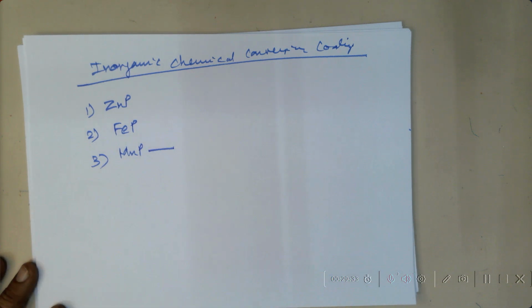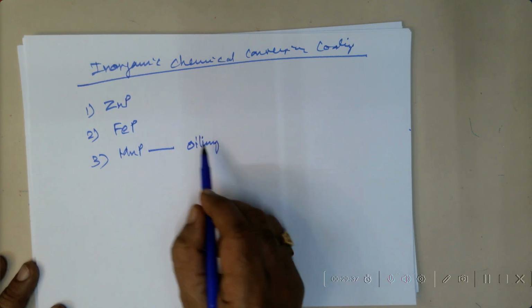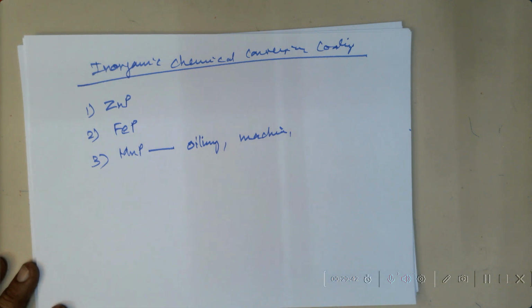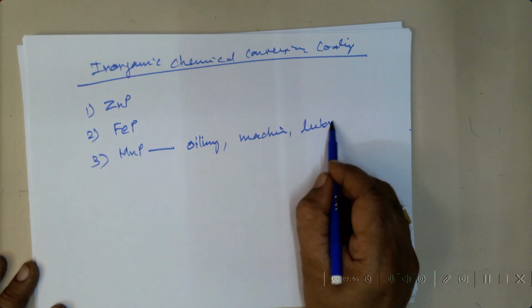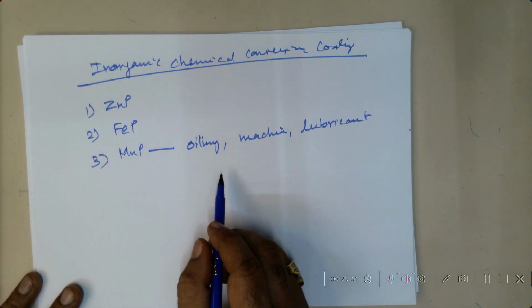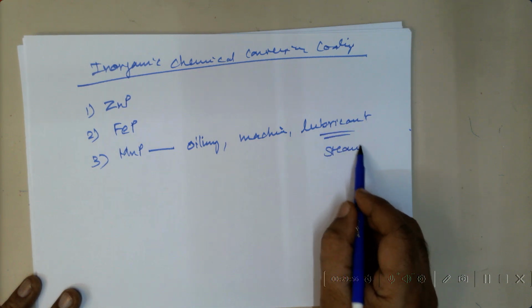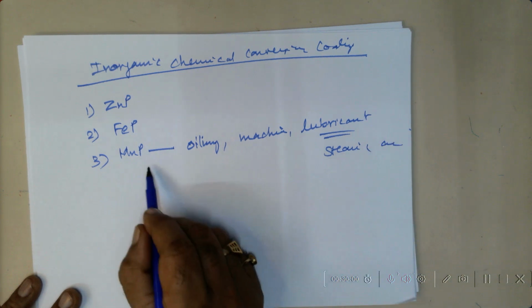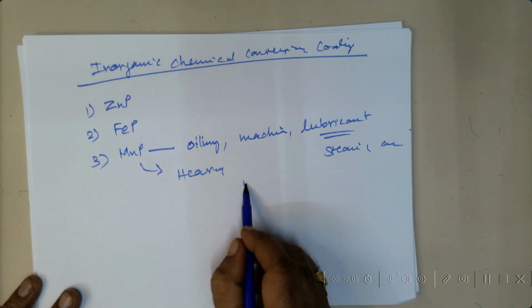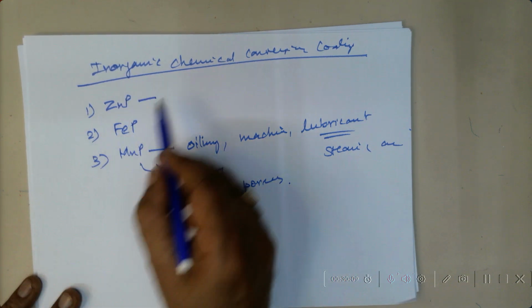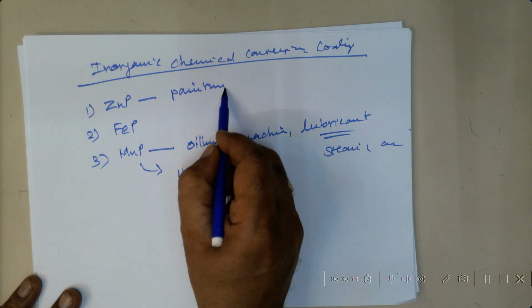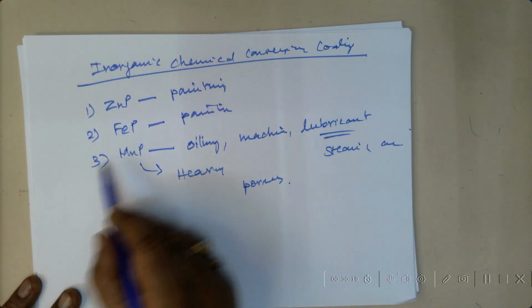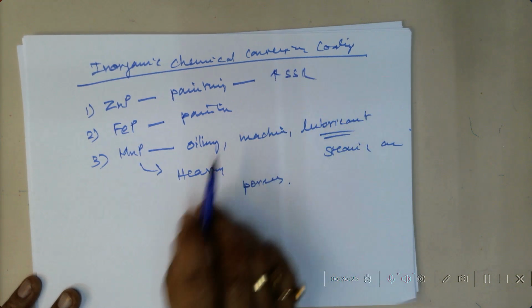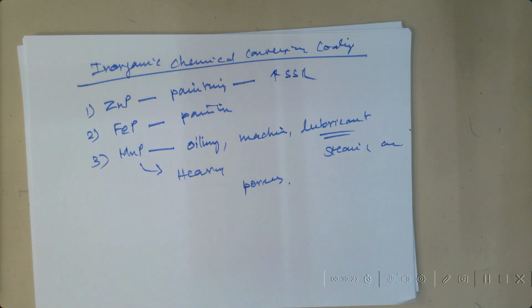Most of the people use manganese phosphating for oiling purpose, for machinery parts or moving parts, or they apply lubricant especially on tubes. They are using stearic acid also. Once they phosphate everything, over which they give stearic acid. Manganese phosphating is heavy. It consists of a lot of pores. Whereas zinc phosphating is intended for painting. This is also for painting, but the zinc phosphate gives a better salt spray resistance. So usually they give an organic top coat in the form of either powder coat or organic liquid paint coat.